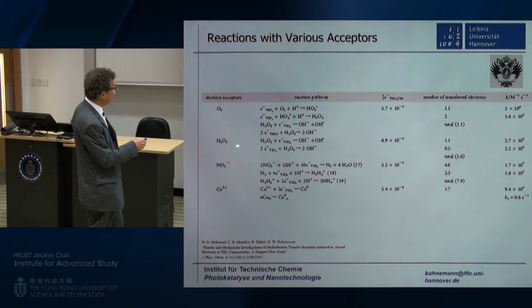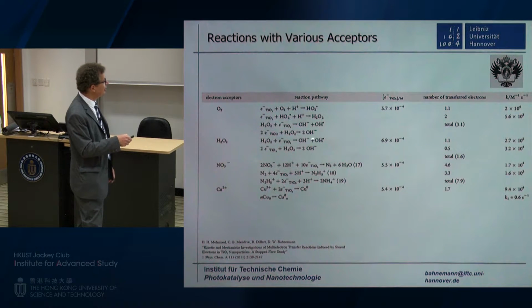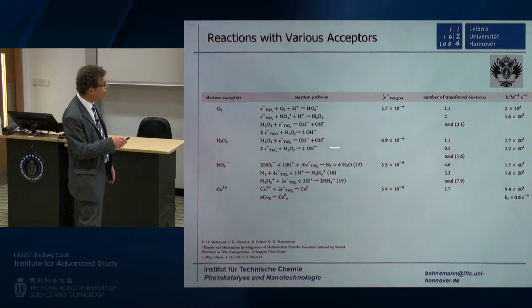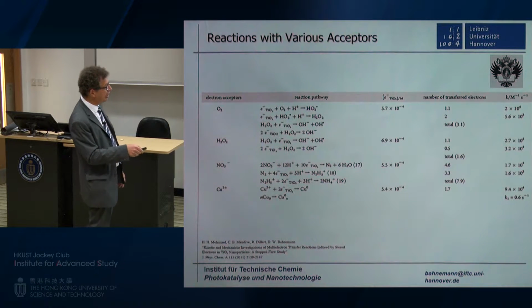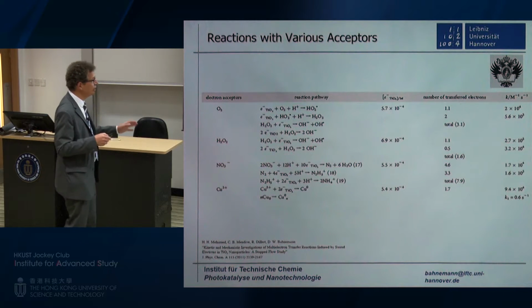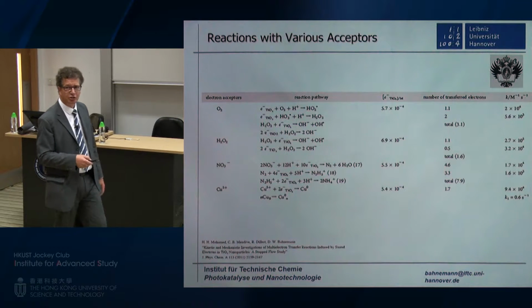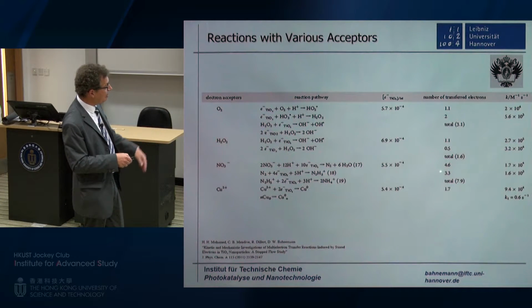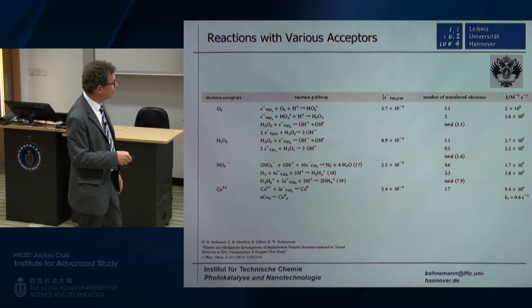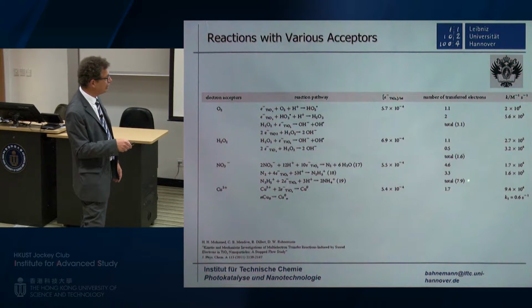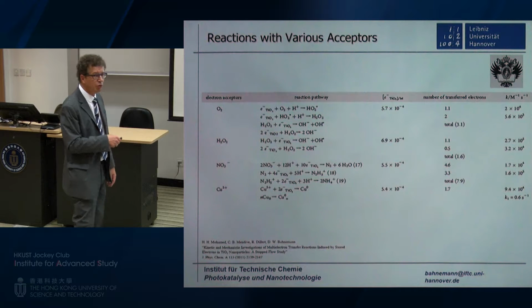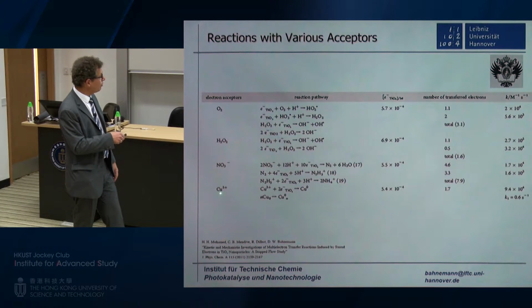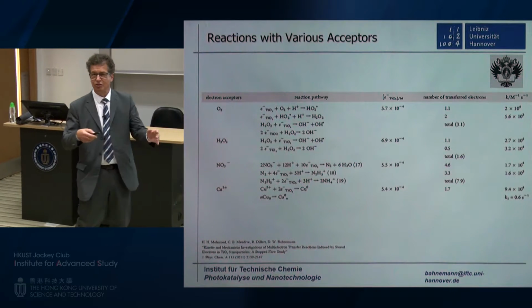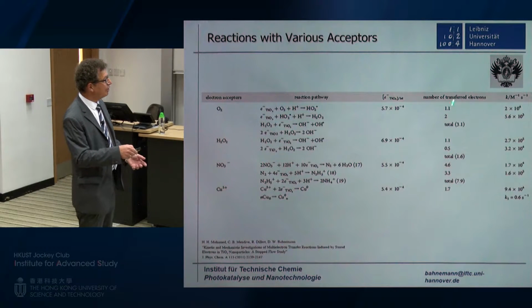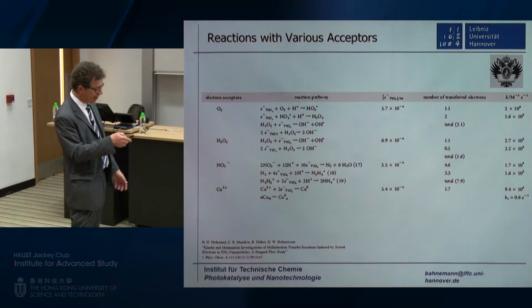You can also take hydrogen peroxide as a reactant, and then you can see its reaction going down. And again, you can follow this reaction stoichiometrically by looking at how many electrons are there, and you can look at the kinetics of this reaction. So you can play around with these things. Take nitrate. Nitrate is interesting because nitrate has, again, a double exponential decay. The first one uses about 5 electrons, the second one about 3 electrons, altogether 8. And 8 electrons means it goes all the way to ammonia in this system. Or use copper 2 plus, which uses 2 electrons going to copper 0. So that is what I mean. You can play with these systems and you know how many electrons are transferred and how fast this transfer goes.